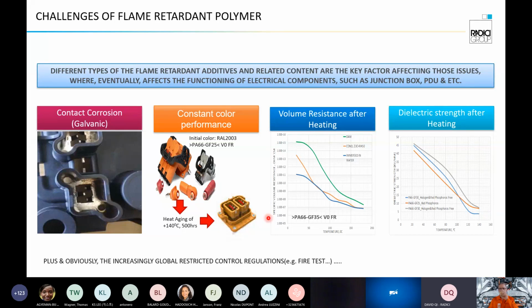Here you can see that the metal part was hybrid injected with plastic, which is flame retardant polyamide. But if the polyamide flame retardant additive is not chosen correctly, then you will confront this contact corrosion phenomenon, which is very dangerous for electrical or electronic devices on new energy vehicles.